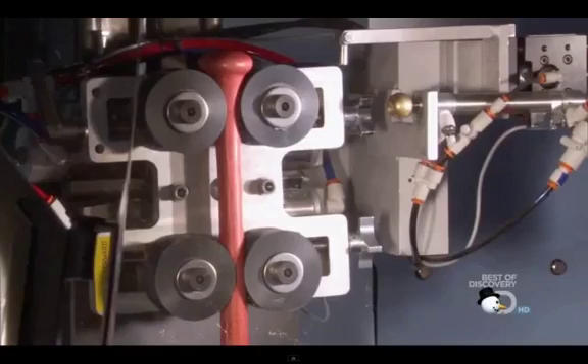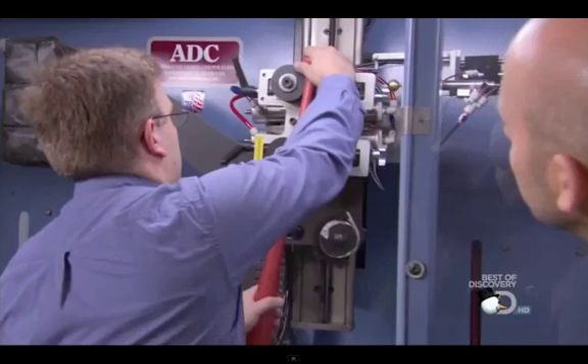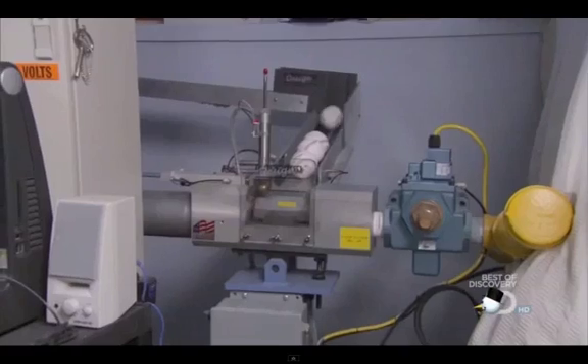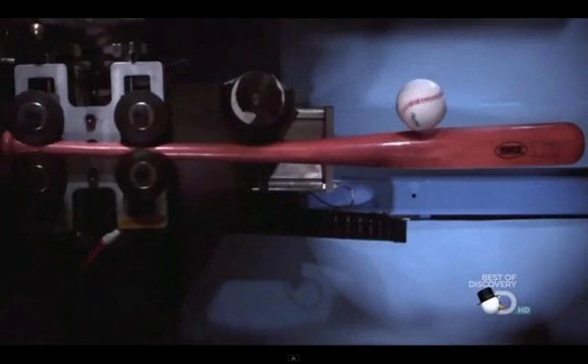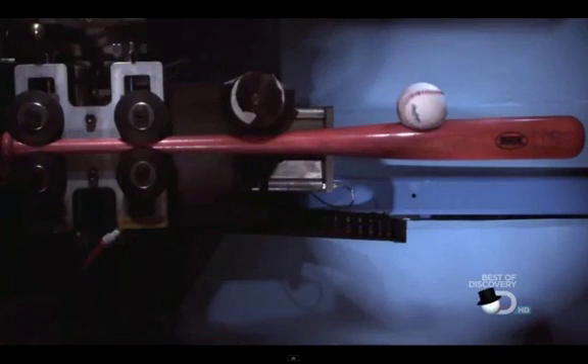What happens if these vibrations get too much for the bat to bear? Now we're moving an inch and a half to two inches further out, and we're going to fire at about 150 miles per hour, which replicates a 90-mile-per-hour pitch and a 60-mile-per-hour swing. We're moving away from the proverbial sweet spot that lies about five to seven inches from the end of the bat. When the ball hits outside the sweet spot, the bat vibrates even more — changing the impact point by only three or four inches puts the bat in almost an S-shape at certain points, which is an amazing amount of vibration.